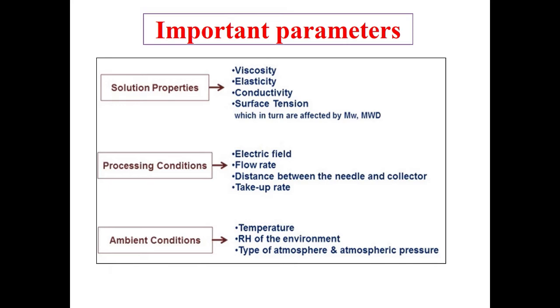Solution properties. When we talk about the solution properties, as I mentioned, viscosity is one of the most important criteria. When viscosity is moderate, then aligning and drawing of the fiber is uniform without any formation of knots. When moderate viscosity is there, it has good elasticity. Elasticity is the property of the material which has the ability to elongate during the drawing. Conductivity is very much important. Surface tension is one of the important parameters, which in turn is affected by molecular weight and molecular weight distribution.